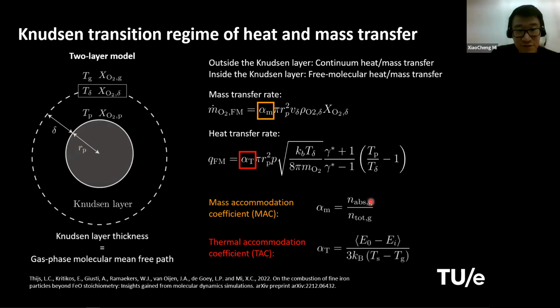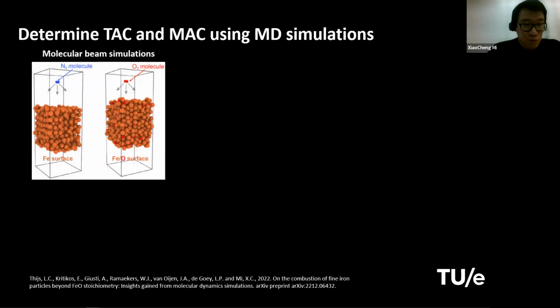But these values for liquid iron and iron oxide surface with oxygen and nitrogen molecules are not available in the literature. So we decided to use molecular dynamics simulations to do this. And this work is mainly done by our PhD student, Leon Theis, collaborating with the PhD student Stratos in Imperial College London. And they performed MD simulations to measure thermal and mass accommodation coefficient for iron surface and also iron oxygen mixture surfaces. And the methodology used here is called the molecular beam simulations.